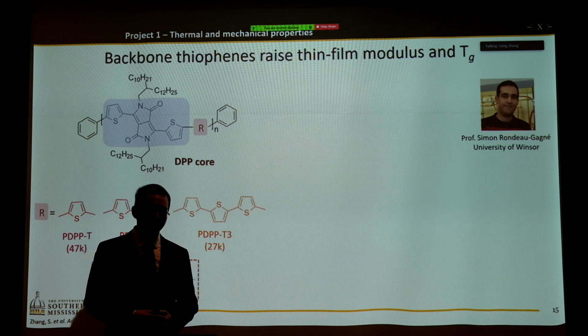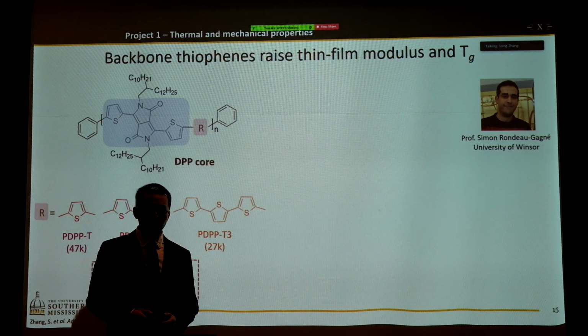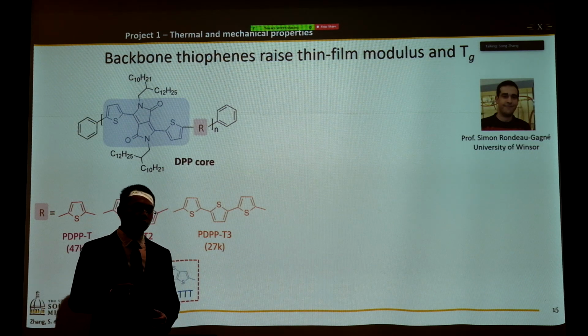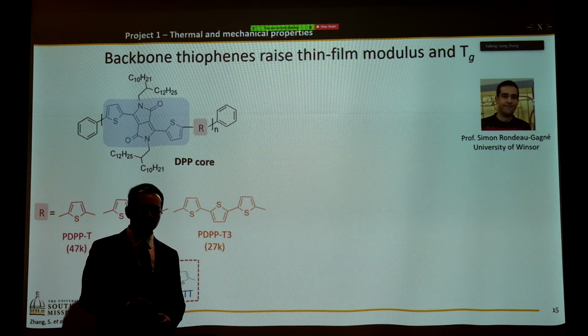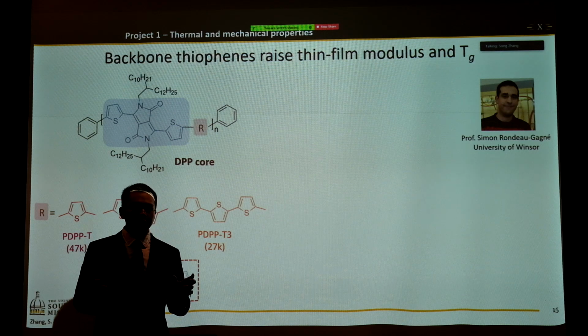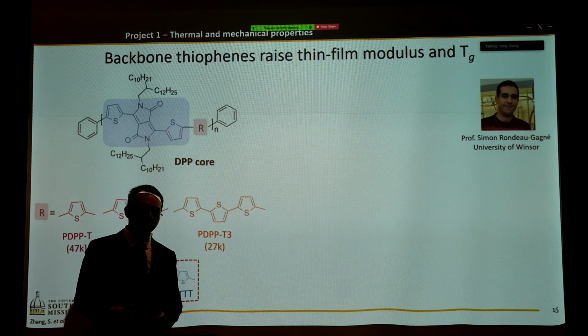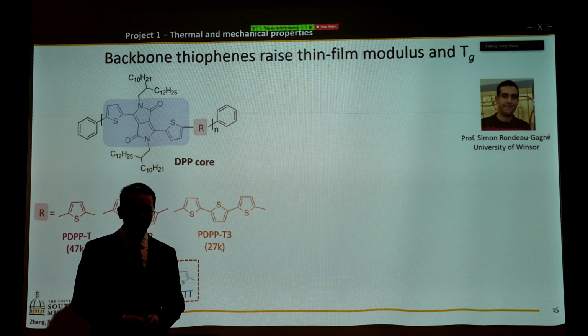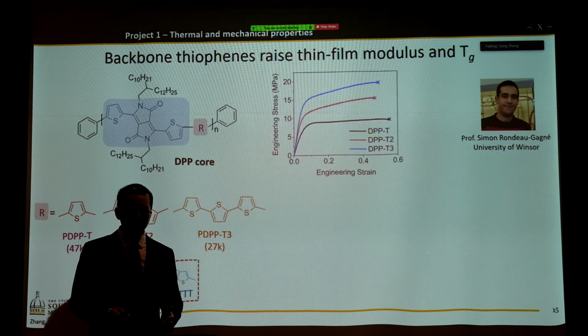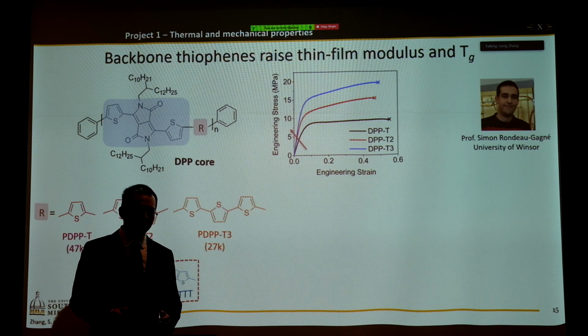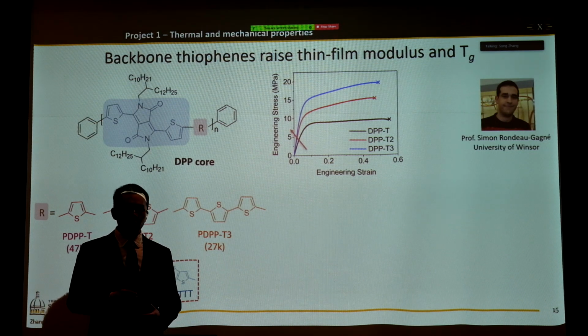For the sake of saving time, I'm only talking about the first three polymers in this talk. Previous literature has suggested that if we incorporate this small ring structure in between a large ring like the DPP unit, we can efficiently lower the backbone rigidity. But from our measurement, it seems to be contradictory, because we do observe an increase in elastic modulus with incorporation